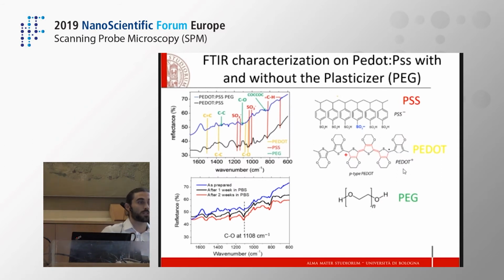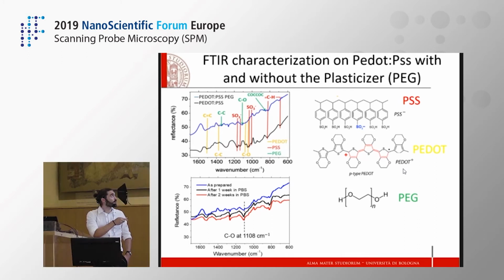We then studied the presence of the PEG inside of our polymeric mixture, and what we did is to use Fourier transform infrared spectroscopy. As one can see from the green arrow, there are C-O stretching vibration bands at 1108 cm⁻¹, together with C-C fingerprints that state the presence of the PEG in our mixture. And this spectrum is kept even after 2 weeks of immersion of our electrode in PBS. Thus the PEG molecules don't leak out from our polymer.